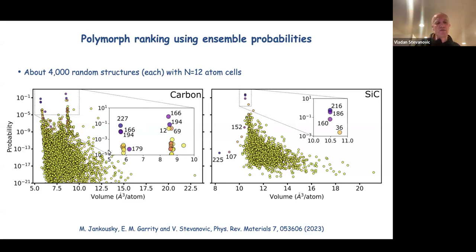And this distribution, if you analyze it a little bit more carefully for carbon, you will identify two peaks, a denser, lower volume peak, and a higher volume peak. And if you look at the top of these peaks, you find what you expect. At the denser peak, you find diamond at the top, and then hexagonal versions of diamond, so space group 166, space group 194. And in the lower density peak, at the top of the peak, what you find are different ways of stacking graphene sheets, so into graphite. So you pretty much find graphite and diamond as known experimentally. And again, we are reproducing experimental results fairly well.